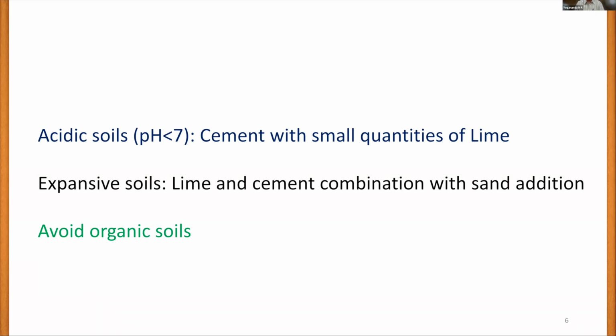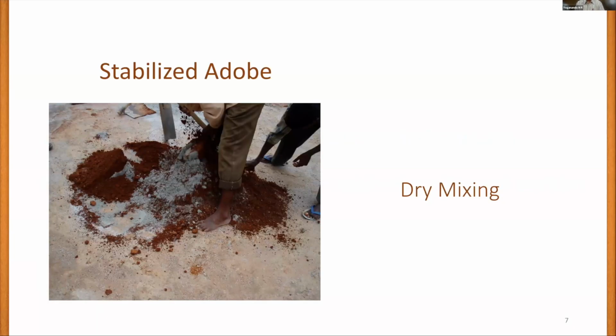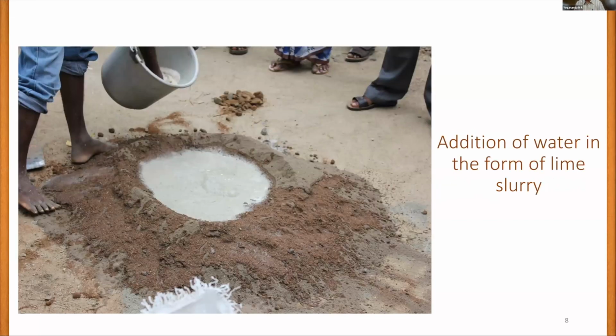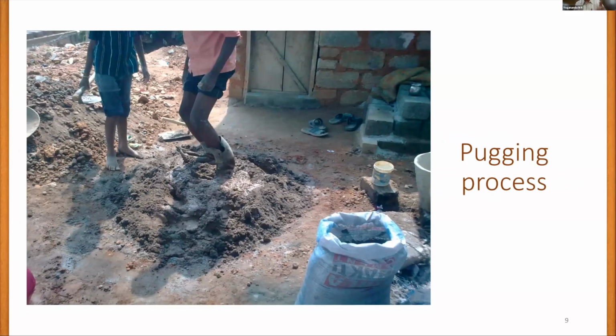So going forward, just to give you an idea of how the stabilized adobe is made, generally the dry mixing happens with the soil, sand-like material, and stabilizers. We add water in the form of lime slurry. That is something which is required. The moisture should be good enough to have a good pugging process, because this is very critical. Mixing is the most critical part of the whole process. The pugging activity should be such that you get a very homogeneous mix after that.